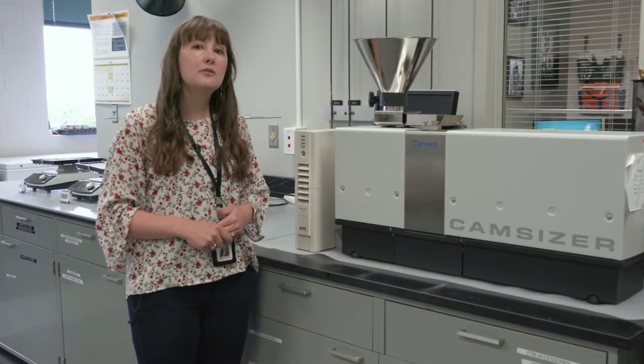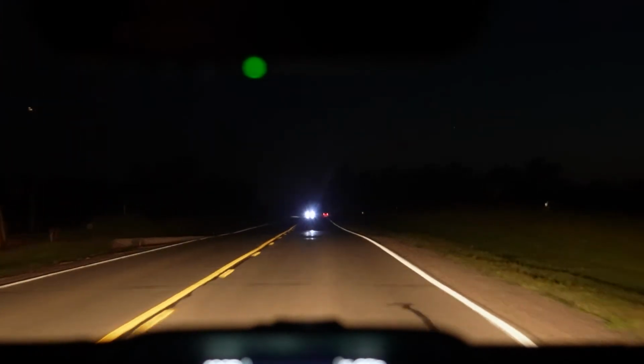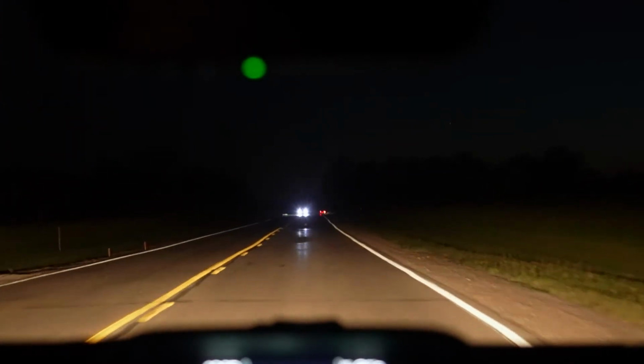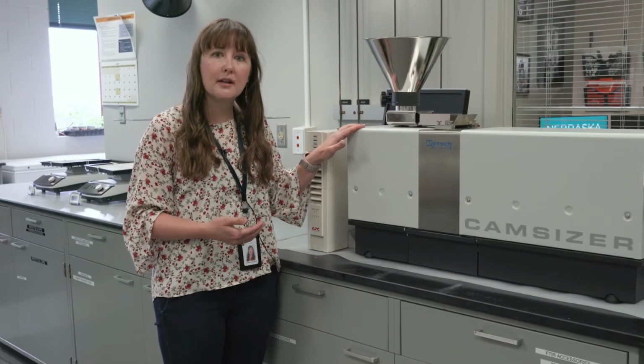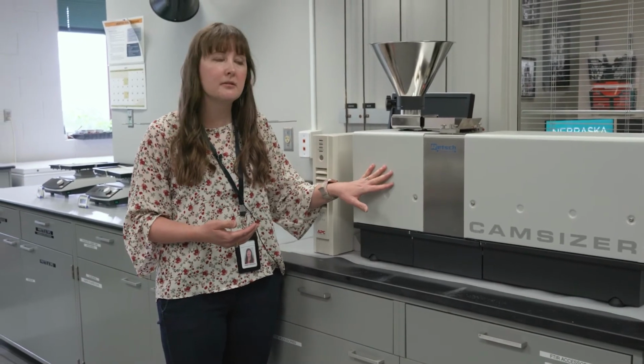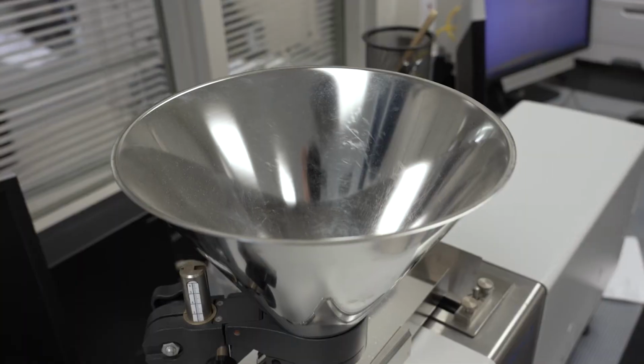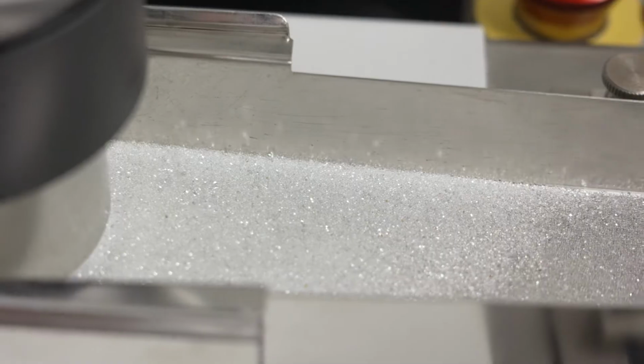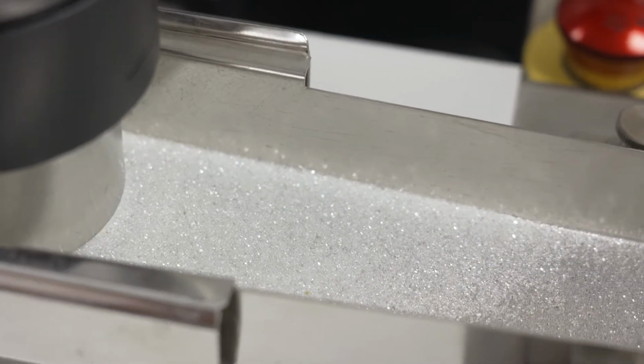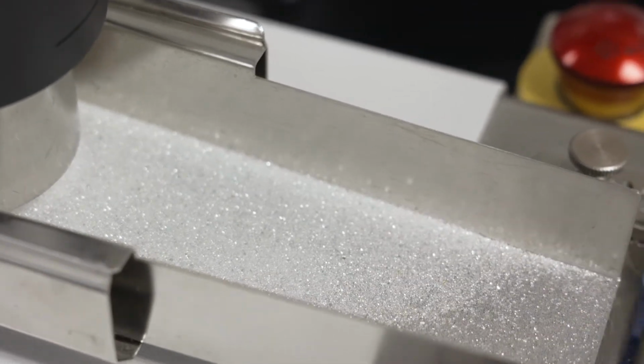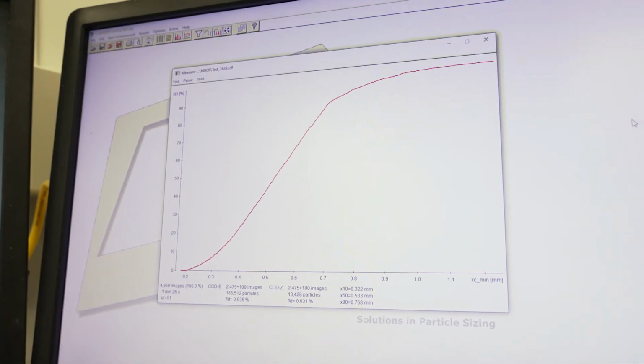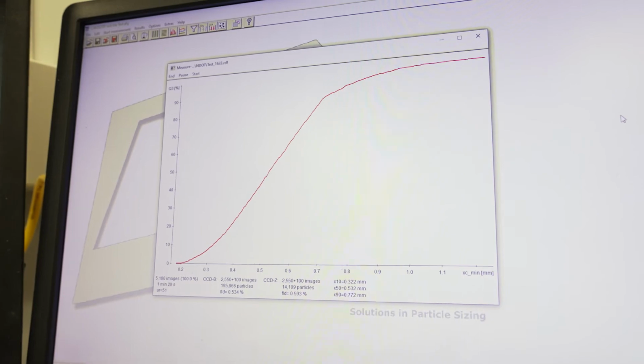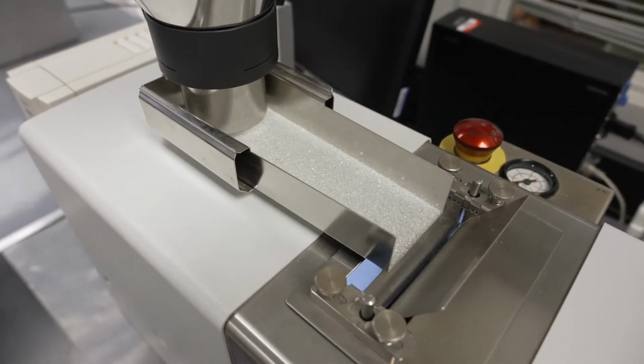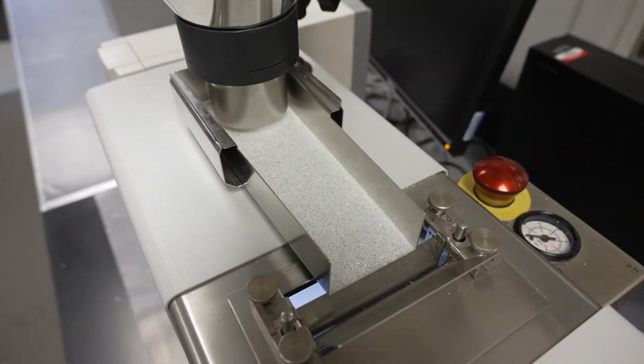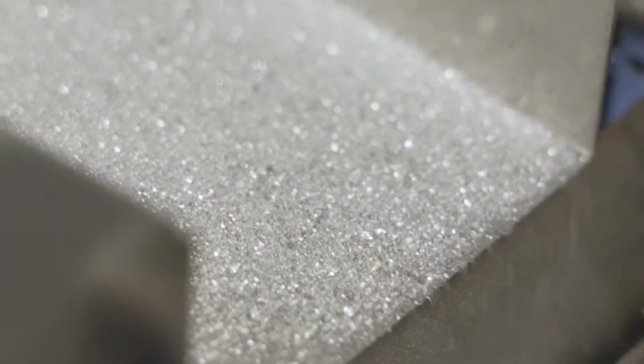Glass beads are used with the traffic paint. That's what is reflecting your headlights. And we have a computerized particle analyzer, which we call our cam sizer, that measures how round the beads are and also the size of the glass beads. We run a sample for 10 minutes. It measures about 2 million beads in that time. It measures the beads at 64 different angles, and it takes 60 images per second.